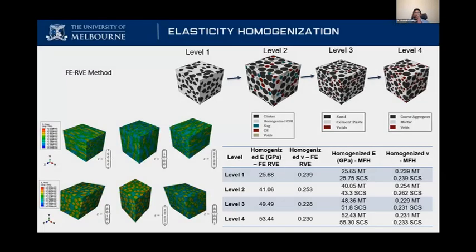So this is an exercise that we did, where we model at level one, which means the micro scale, and we upscale that to the concrete level. This is an example for elastic modulus, like how we did that. We did the nano indentation at this scale, then we use that result and upscale to find the result in the structural scale. So from a micro scale, nano scale test, now we can predict what is happening in the macro scale. What we need is a small piece of concrete sample. That's enough to do this.